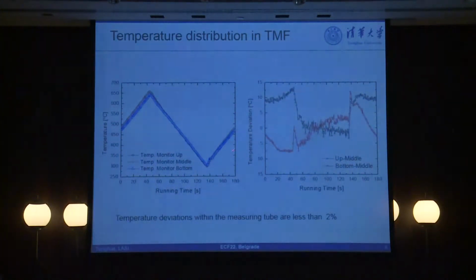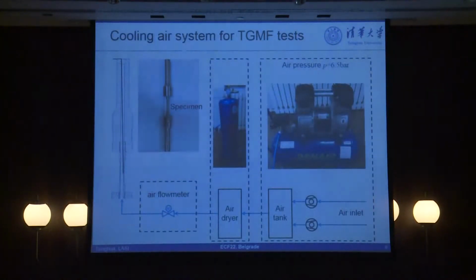And this thermal load will be combined with mechanical load. That means the mechanical load is all in the same state actually. Okay, we can change the so-called phase angle between the mechanical load and the temperature load here. And in our specimen, of course, if we're talking about the TGMF, we additionally introduce cooling into the tube to introduce the temperature gradient. Okay, then you pump the cooling air into it, to introduce the temperature gradient.